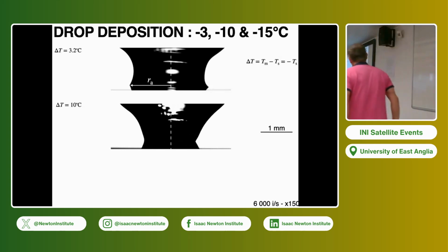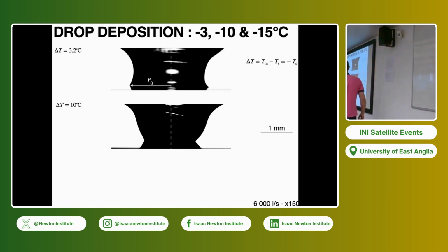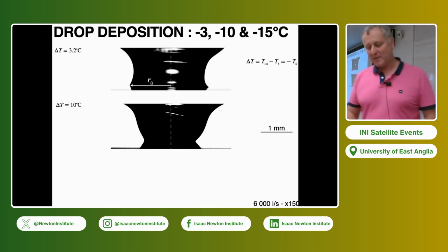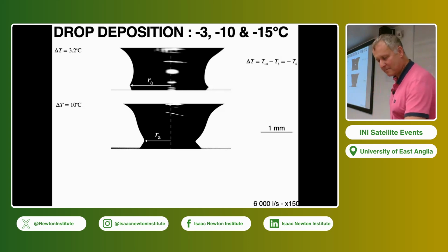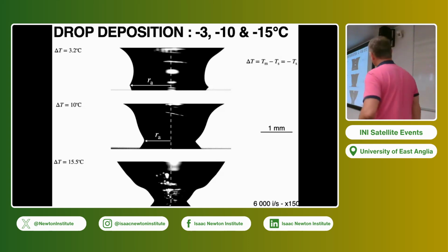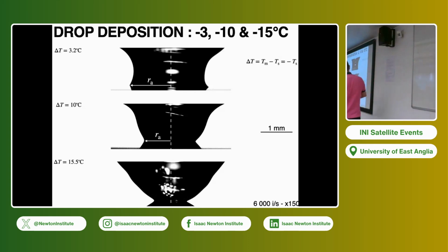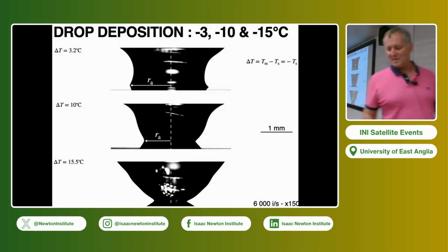Let's do the same one at minus 10 degrees. First obvious observation, it does not spread as much. So definitely the fact that there is solidification slows down or stops somehow the spreading. If you go even further, minus 15.5, you see again that it stops before, and here it looks almost symmetrical, as if the spreading was axisymmetrical. Here left and right are definitely not so clear, so maybe we have lost some symmetry.